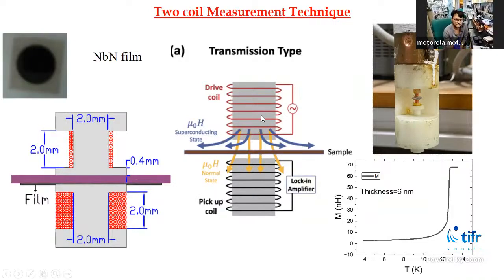Taking the Meissner effect into account, we do a two-coil measurement technique. First we send some current through our driving coil, which is basically a solenoid, so it can generate some magnetic field. When it's above TC, the sample is not superconducting, so all the magnetic field developed by this drive coil is picked up by the pickup coil. So above TC, you can see here the magnetization, in the nanohenry order, is higher.